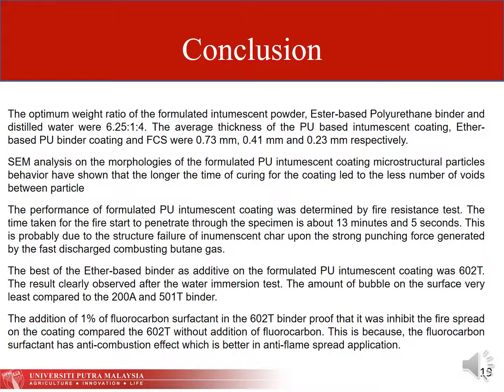Comes to conclusion. The optimum weight ratio of the formulated intumescent powder, ester-based polyurethane binder, and distilled water was 6.25 to 1:4. The average thickness of the PU-based intumescent coating, Ether-based PU binder coating or the FCS coating, was 0.73 mm, 0.41 and 0.23 mm respectively. SEM analysis on the morphology of the coating has shown that the longer the time of curing, the fewer voids between particles.